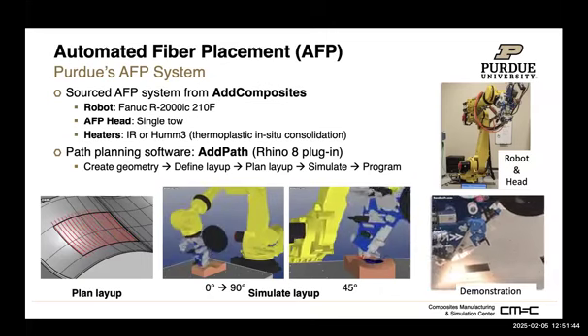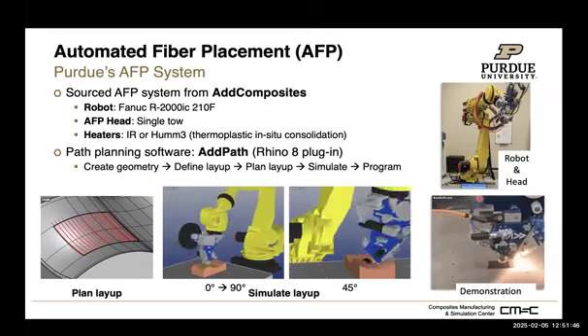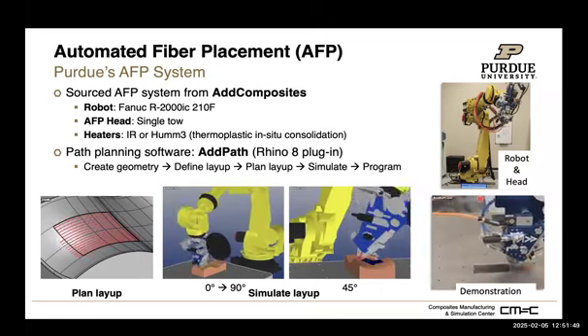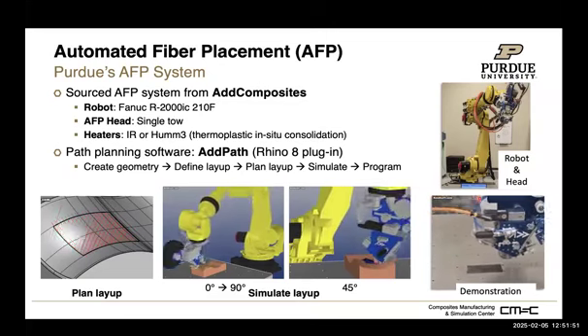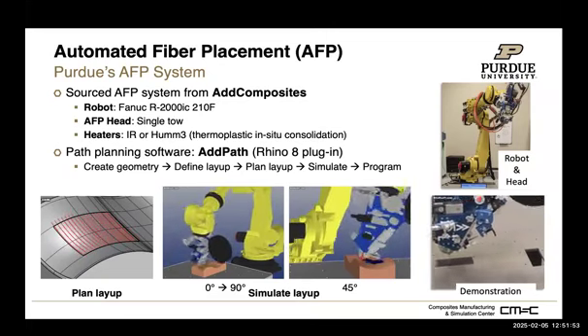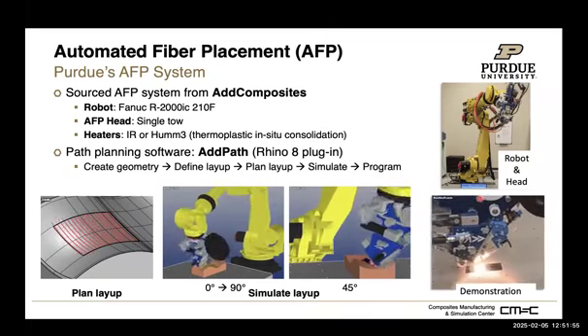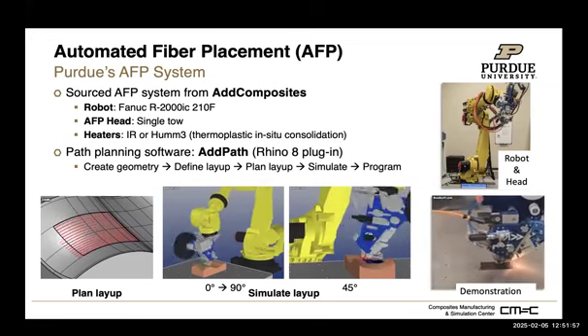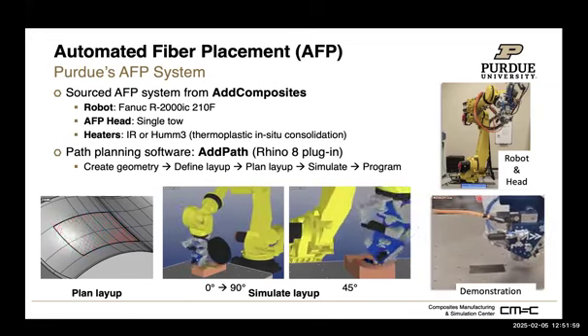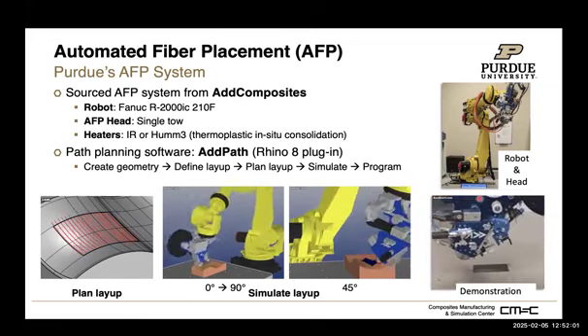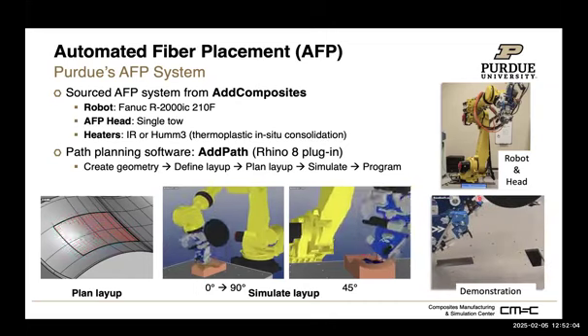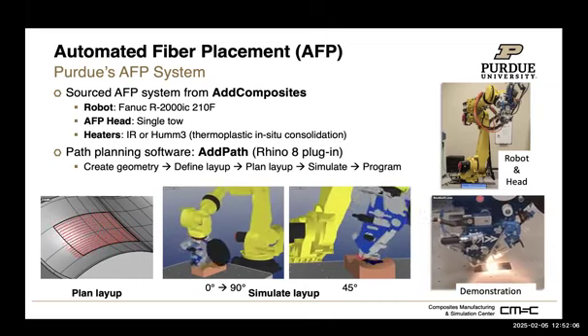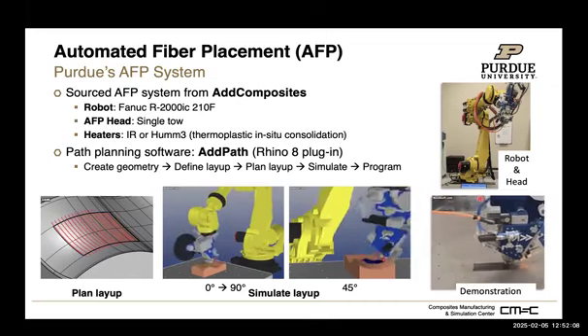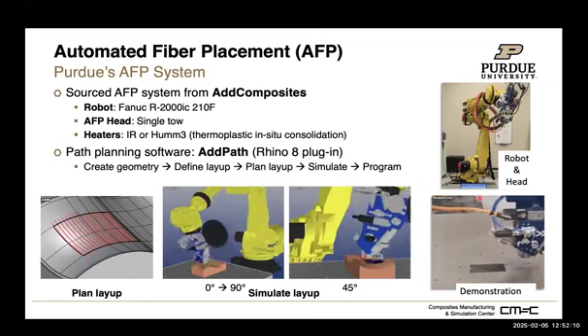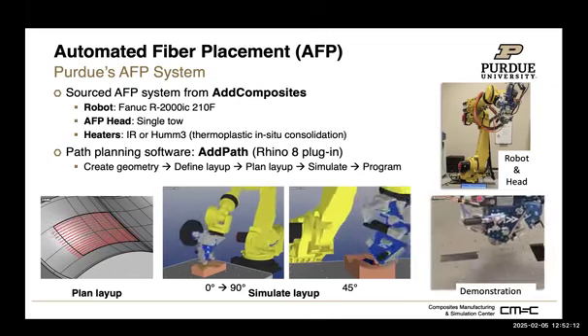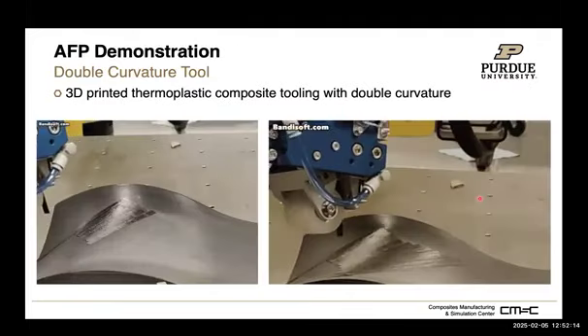But if you look at the angles of the fibers being used, it's typically just 0, 90, plus or minus 45. Sometimes you will see 30 or 60, but you never see any mystery angle, like 37 or 21 degrees, because from the manufacturing perspective, this is not something you can easily control. Now with the robot, we can lay down the fiber precisely in the orientation we want. So it's very cool technology nowadays.